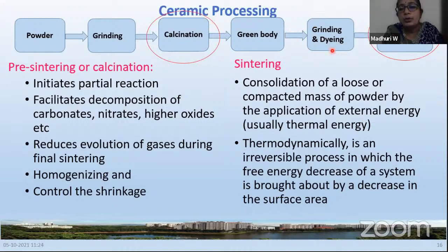Now, once you die-press and form the required shape of your material, then you will sinter it at a higher temperature. Usually, the temperature difference between your calcination and final sintering temperature would be approximately 200 to 250 degrees centigrade or more. A minimum of 150 to 200 degrees centigrade is always advisable. Your calcination temperature should be at least 200 degrees centigrade less than your final sintering temperature. And usually, most of these ceramics are heated at temperatures around 1200 to 1600 degrees even. Fine. So that is the temperature where these materials have to be sintered and formed. That much temperature is required for the material to form the required structure.